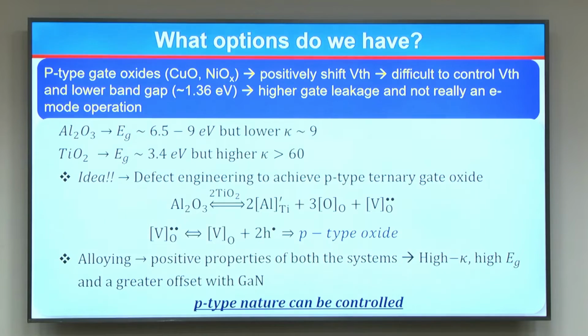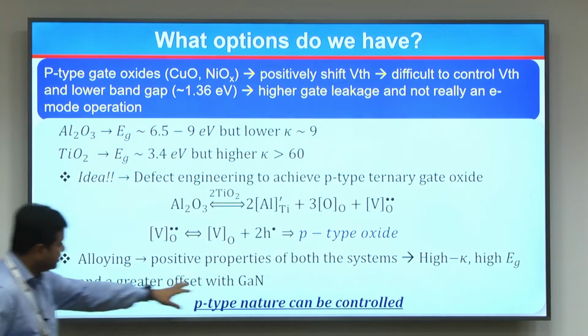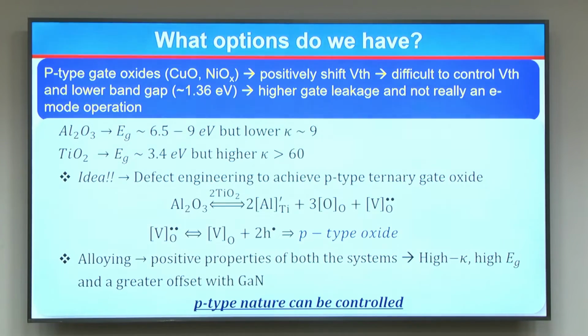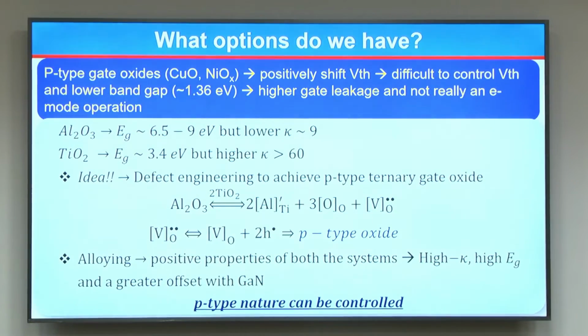So then, because of this accidental discovery, we started exploring this idea: what if you dope TiO2 with aluminum oxide, or in principle what if you dope TiO2 with aluminum, or in this case what if you alloy TiO2 with aluminum oxide. So if you look into this reaction diagram, what it leads to is negatively charged aluminum sitting at Ti sites, and it leads to positively charged oxygen vacancy sites, which basically results in the neutral oxygen vacancy and the holes. These free holes basically make the oxide p-type, right. So now we have a p-type oxide which can be used, and here the p-type characteristic, or the extent to which it is p-type, can be controlled by the amount of aluminum in the TiO2, so the amount of aluminum alloying you do in TiO2.